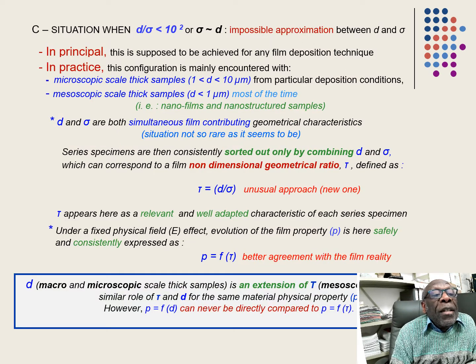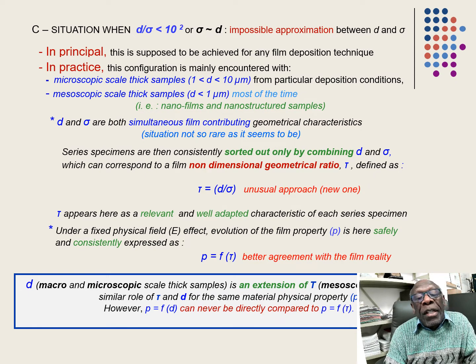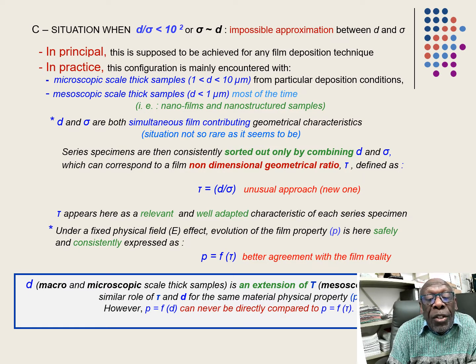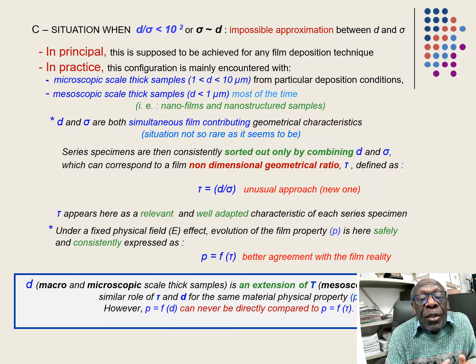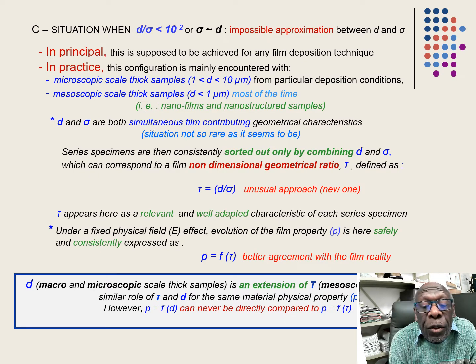The third situation is the ratio is inferior to 10 to 2. That means the values of D and sigma are very close. In that case, approximation is impossible. This is the case. Generally, it's not so rare as we can imagine, because you can find this with nanofilms and nanostructured samples. In that case, both characteristics are simultaneously contributing geometrical characteristics. So, how to find the solution in that case?